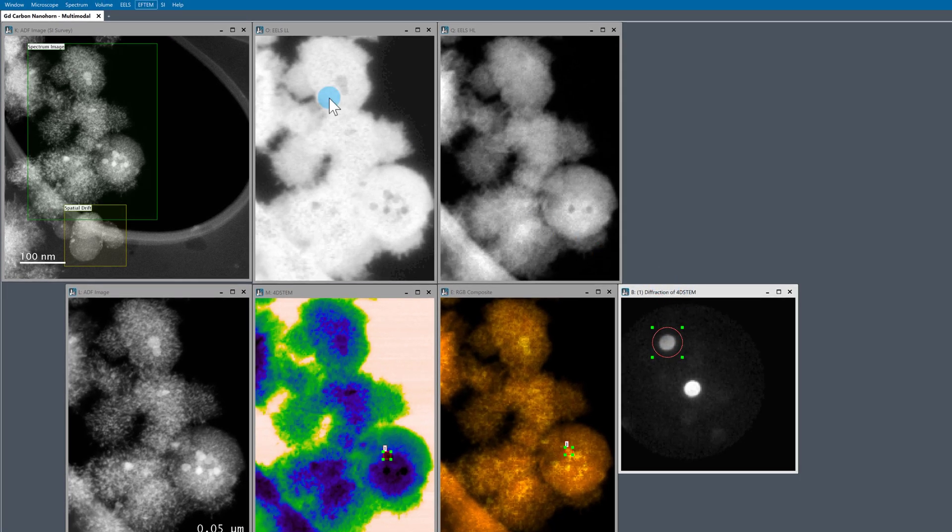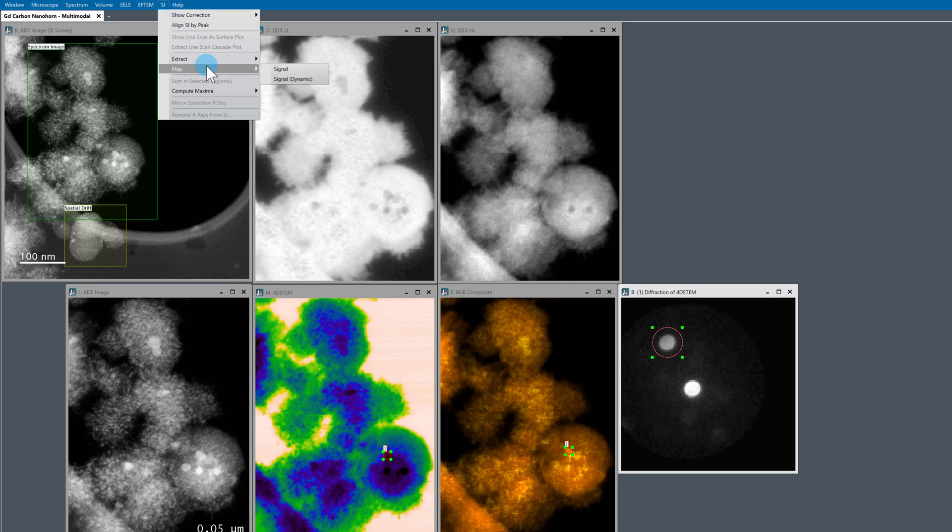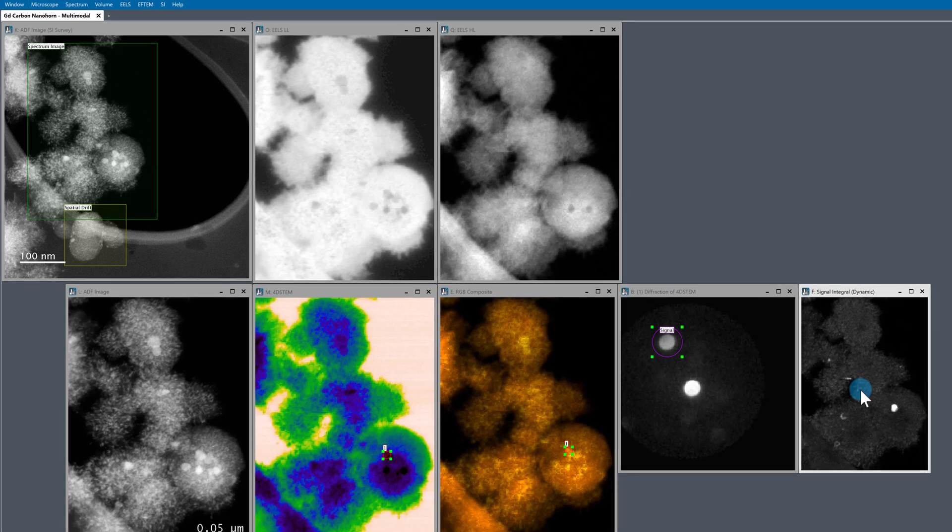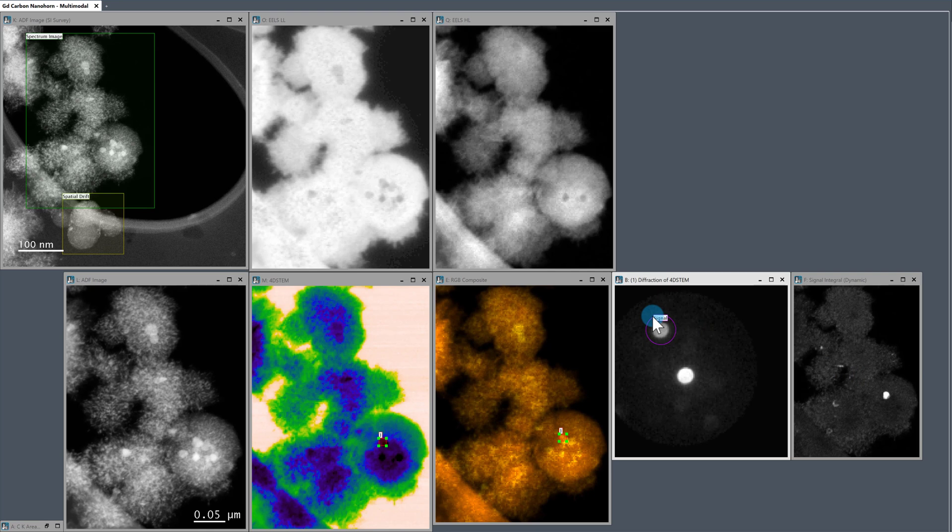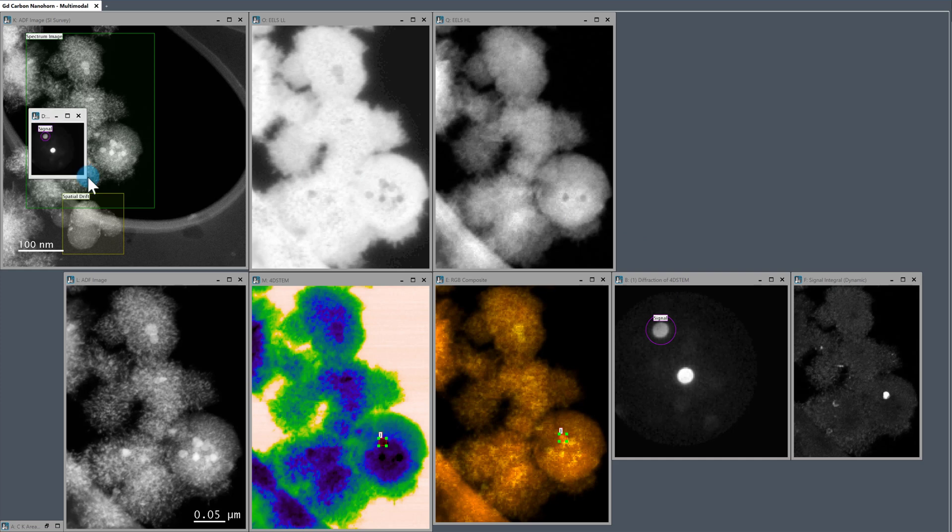And then I'm going to go to the SI menu and press map signal dynamic. So I have a virtual dark field image using virtual apertures, and this virtual dark field image is formed from this diffraction disk. So I'm going to do this for three different regions. And I like to duplicate these as I go along. So I'm going to copy and paste that diffraction pattern into a new image window, put that up there, do the same thing with the map that that diffraction pattern corresponds to.